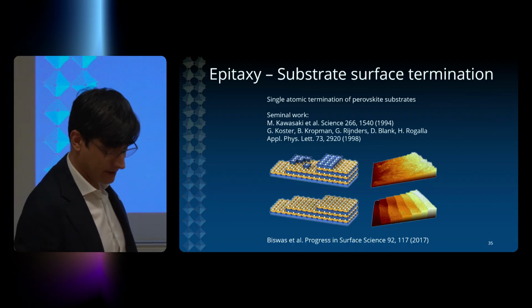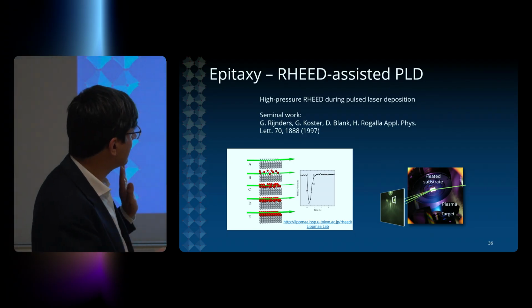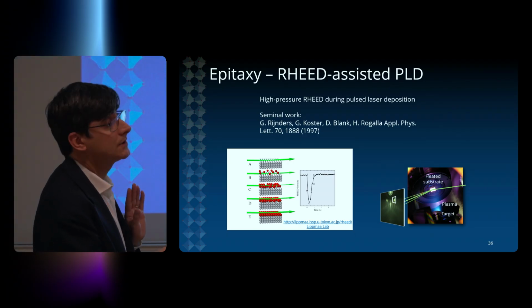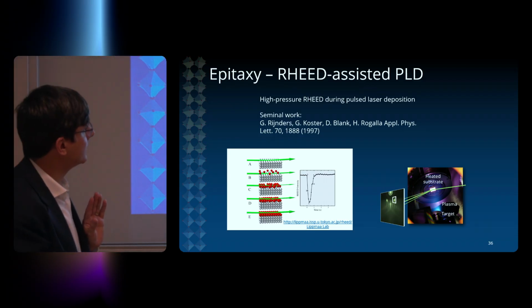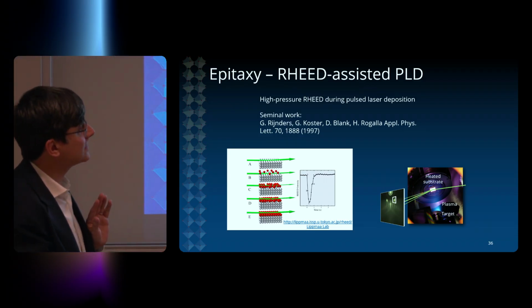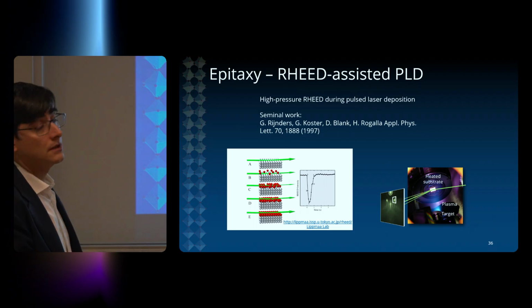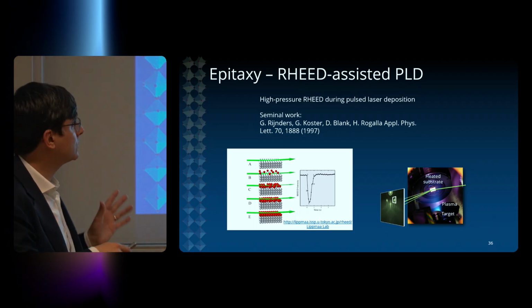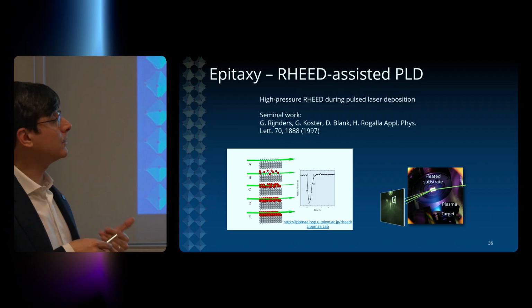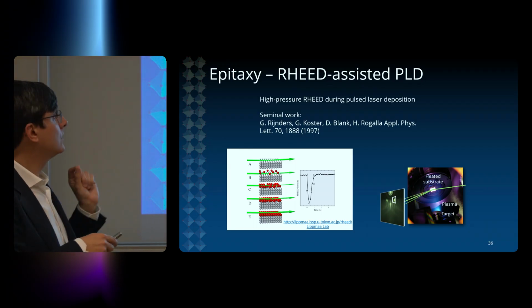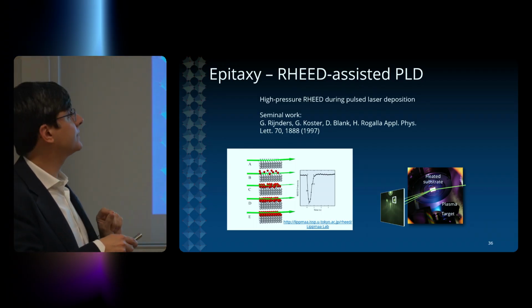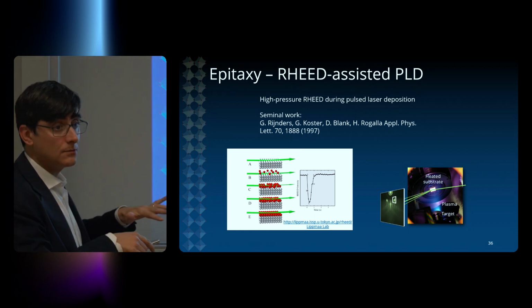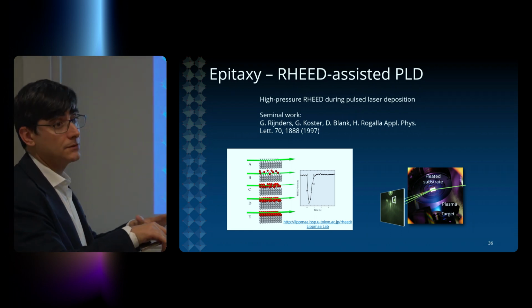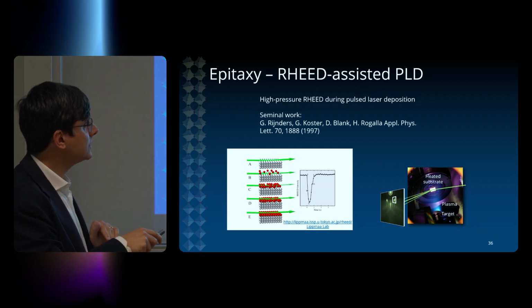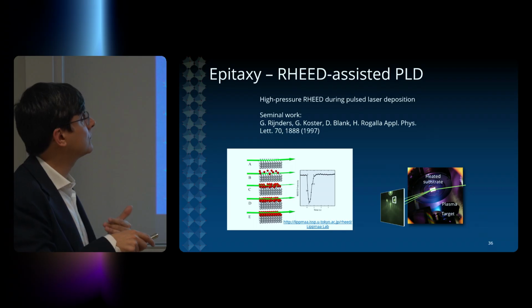Okay? And we use techniques that allow us to deposit single layers of atoms on top of our substrates. This one is called pulsed laser deposition. So we use a laser to create the atomic cloud that is then going to deposit. And during the deposition process, we can use an electron beam to probe the growth process. So we can follow these atoms coming onto the surface, arranging themselves to create a perfectly flat structure. And we see this by following oscillations of the intensity of a diffracted electron beam.